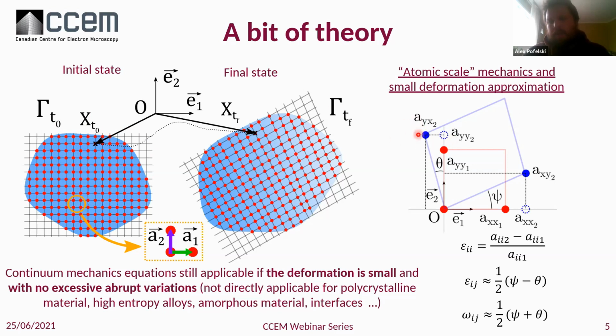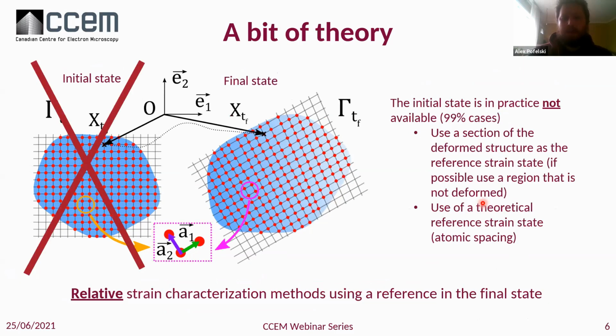So on the right, you have the basic description, very common. You will have in red your reference that you choose. In blue, you overlap this with your unit cell that has been deformed. And by just making some comparison of the distances and angles, you will find the strain components: the uniaxial deformation, the shear, and the rotation. And that's very, very common and very easy to use. That's basically the idea.